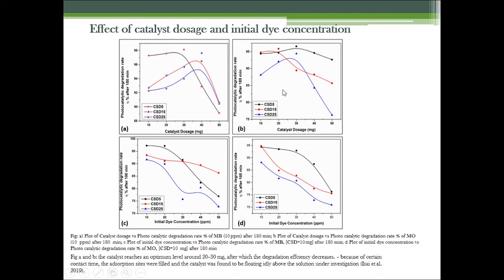This slide shows the effect of catalyst dosage and initial dye concentration. We have conducted a series of experiments to evaluate the optimum catalyst dosage for the effective degradation of the dye solution. The percentage degradation rate was found in each case, and a comparison graph was plotted to know the optimum dosage of catalyst for effective degradation of methylene blue as well as methyl orange dye. From the figures, it is evident that the catalyst reaches an optimum level of around 20 to 30 milligram, after which the degradation efficiency decreases.